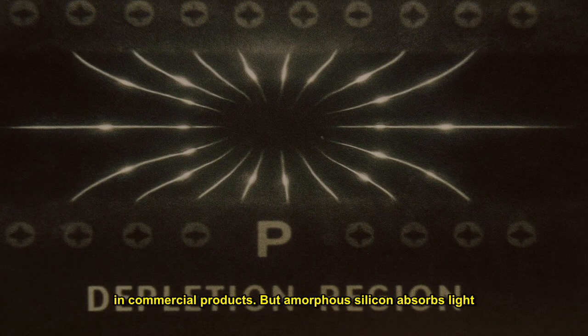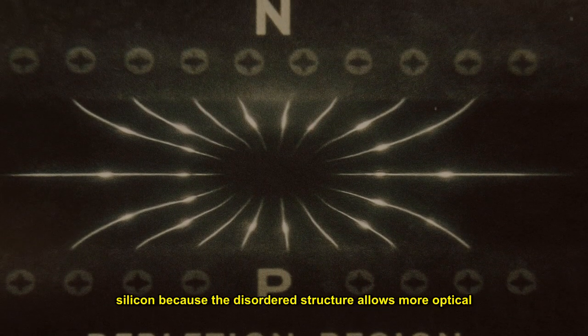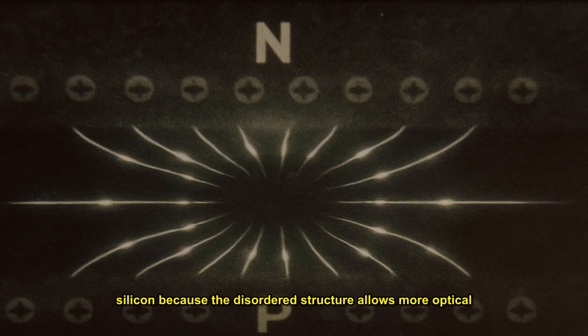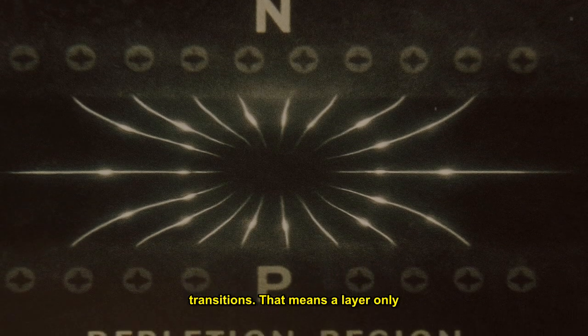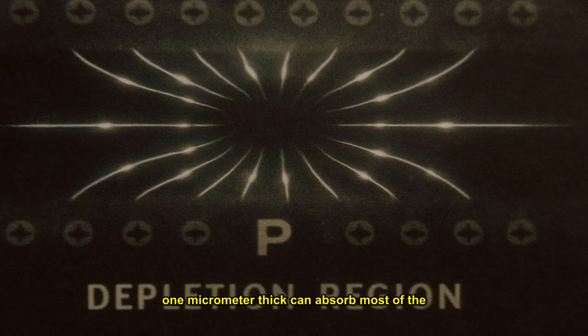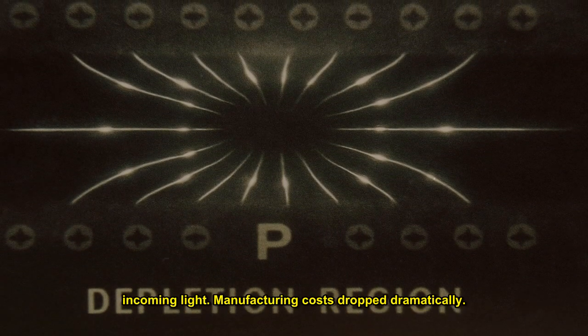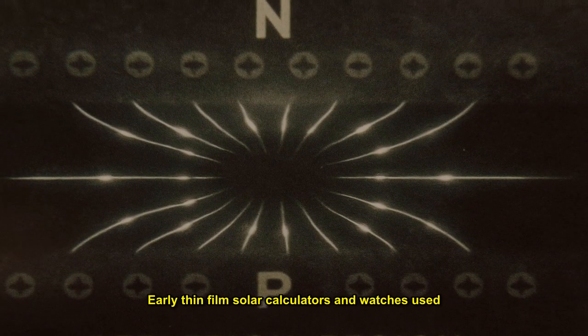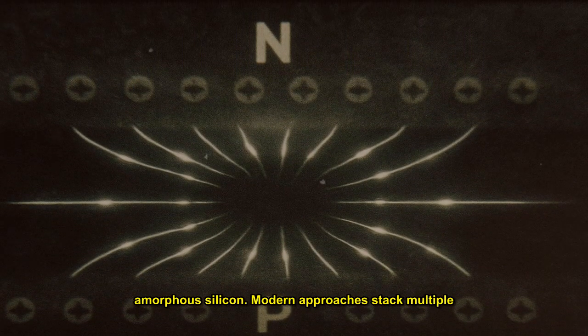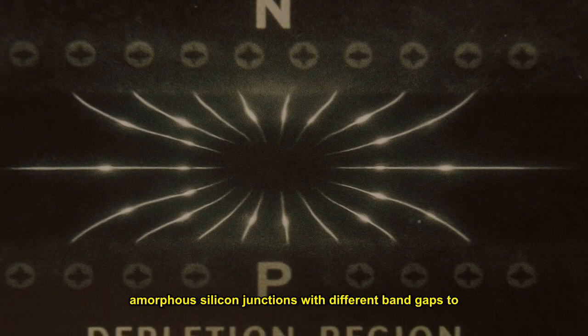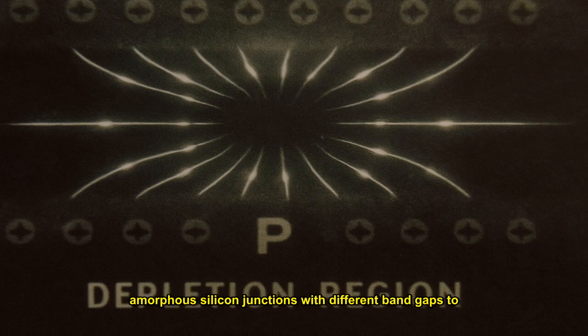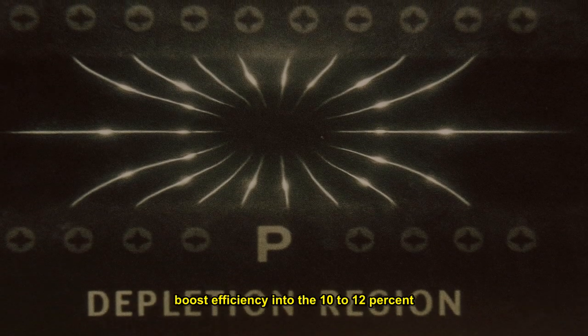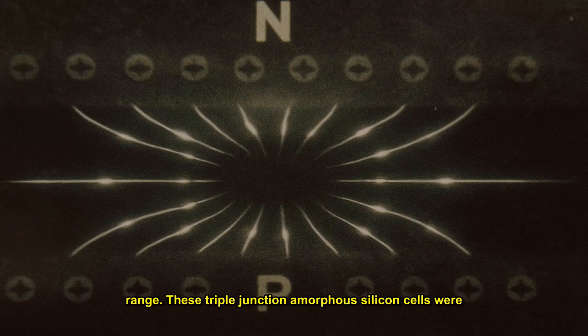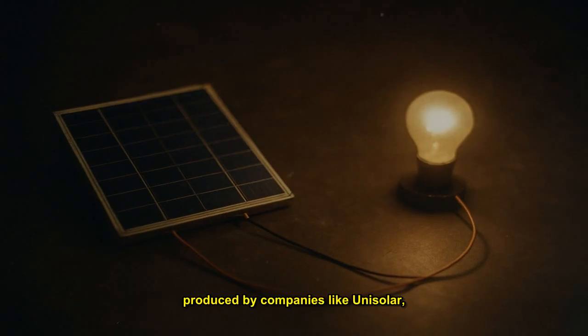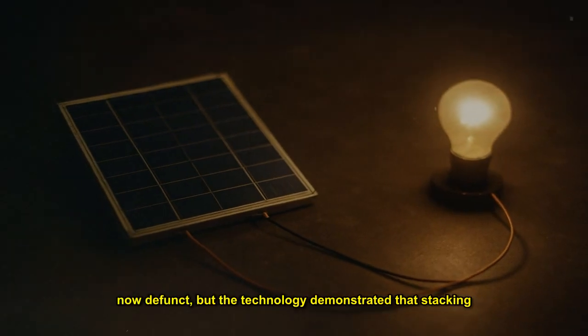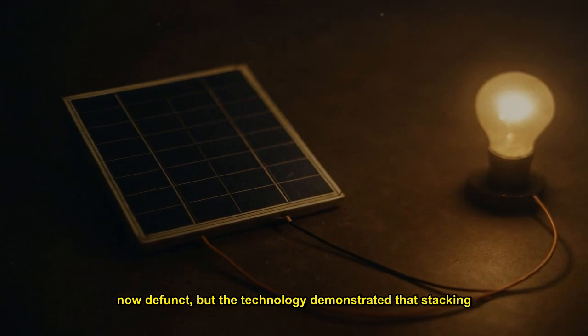But amorphous silicon absorbs light much more strongly than crystalline silicon because the disordered structure allows more optical transitions. That means a layer only 1 micrometer thick can absorb most of the incoming light. Manufacturing costs drop dramatically. Early thin film solar calculators and watches used amorphous silicon. Modern approaches stack multiple amorphous silicon junctions with different band gaps to boost efficiency into the 10 to 12% range. These triple junction amorphous silicon cells were produced by companies like Unisolar, now defunct, but the technology demonstrated that stacking